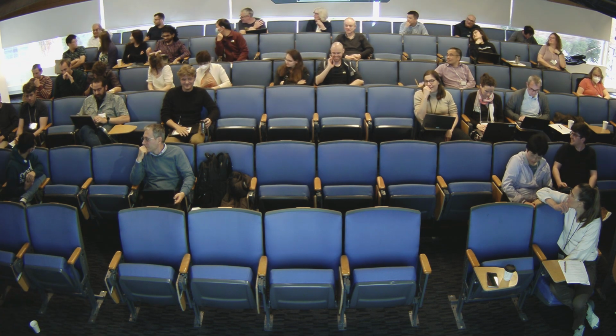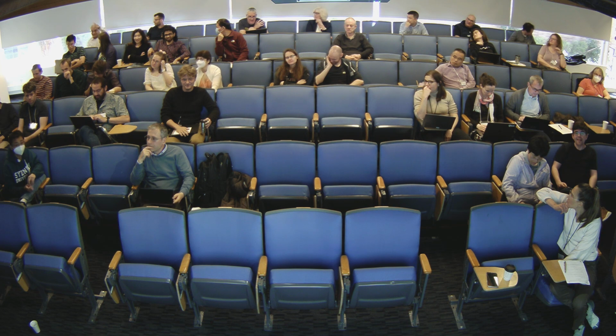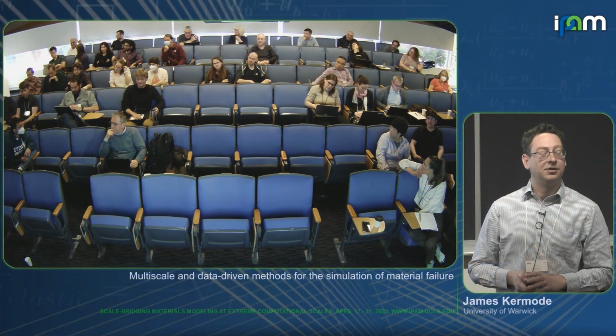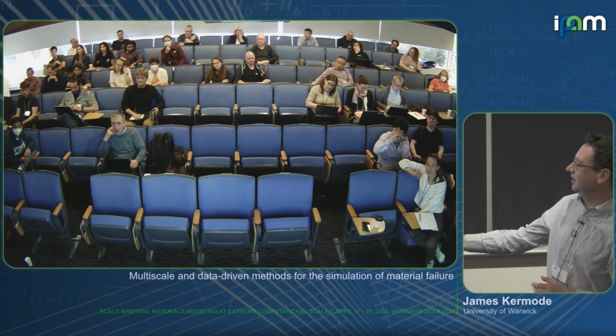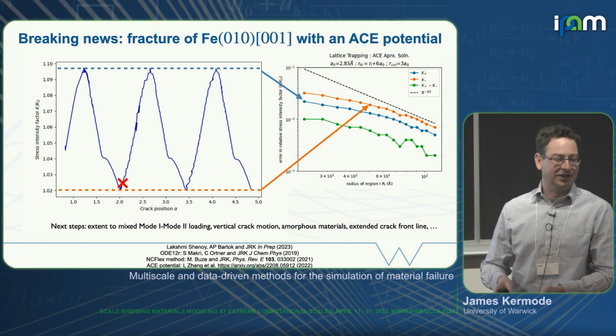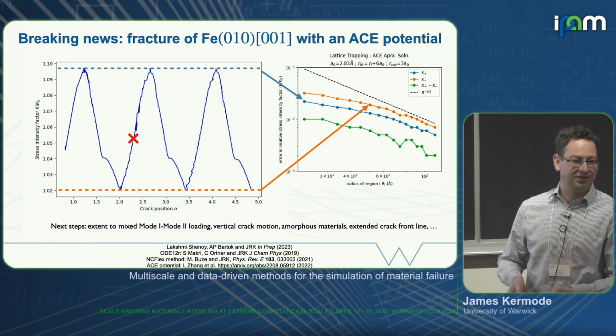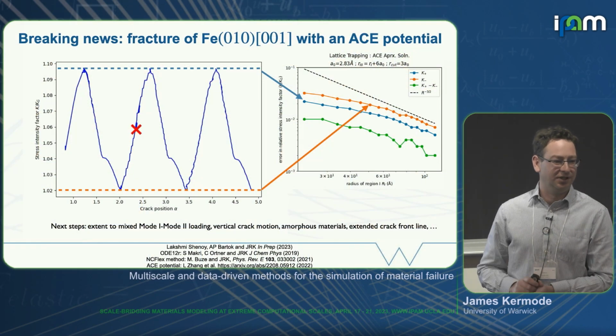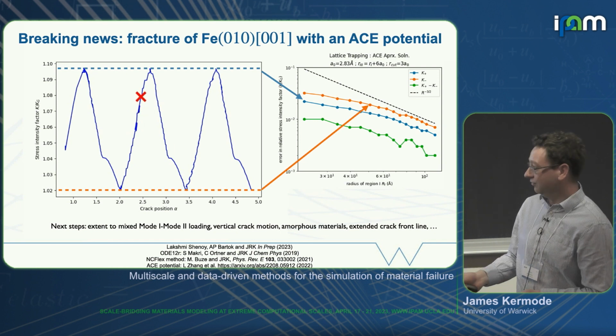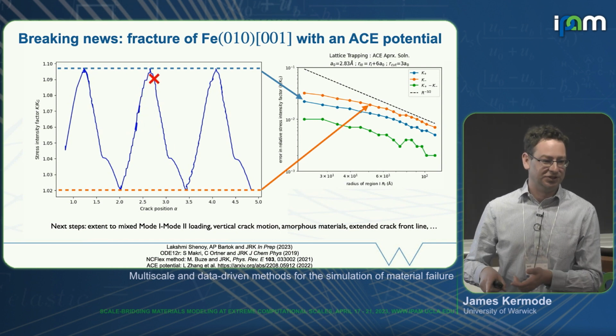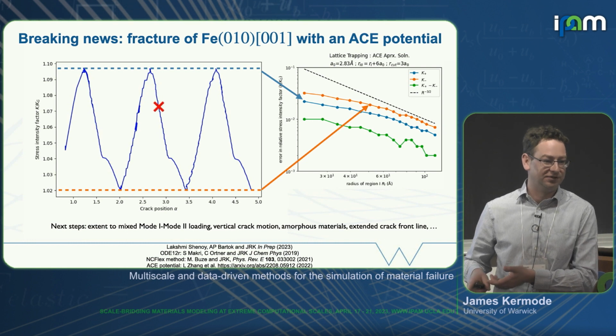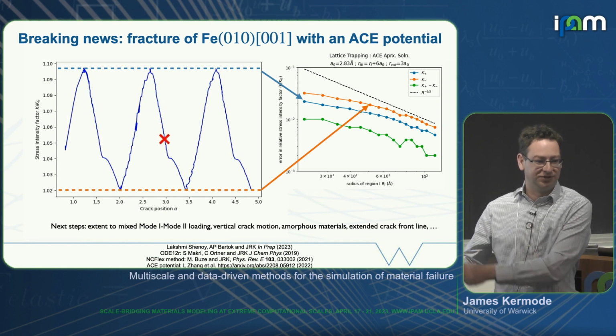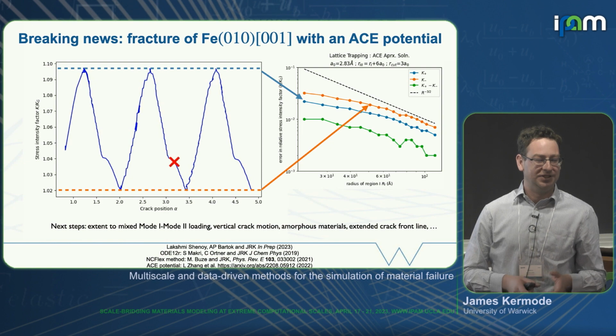Question at the back. So I'll go back to the previous one. You're just testing whether you're able to do the path following continuation? Because in reality this won't happen. No, that's right, but what it gives us insight into is the range of stability for real cracks. We can map out K plus and K minus, the stress intensity factor range over which fracture is stable. And we can also read off energy barriers so that we can make predictions for speeds of kinetic crack growth at low temperatures. So we can get real observables from this technique.